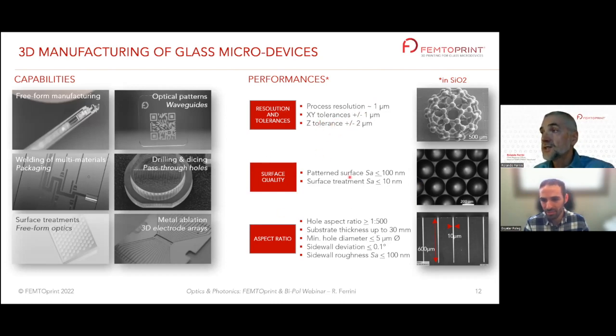Surface quality, already said. Standard process, hundreds of nanometers in terms of average surface roughness, post-treatment below 10 nanometers. If you think about drilling holes, we have a hole aspect ratio which goes up to 1 to 500. We can really drill holes through very thick slabs, up to 3 centimeters. The minimum hole diameter is 5 microns. Sidewall deviation, as I said, 0.1 degrees, and the sidewall roughness is nice. It is below 100 nanometers, which is better than what you can get with laser ablation.